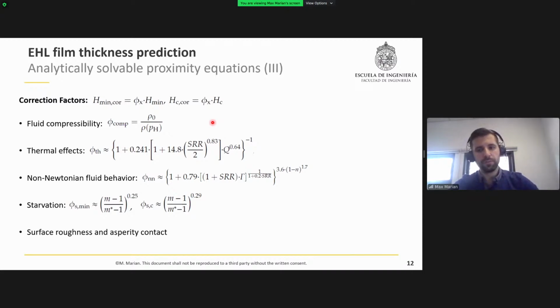We know that the lubricant compressibility plays no major role in the minimum film thickness formation, but the central film thickness formation can be influenced under certain conditions, and therefore we can adjust the predictions for compressible fluids from the incompressible approximations with the base density rho 0 using this kind of correction factor, whereby any model could be used to calculate the density at the respective Hertzian pressure pH.